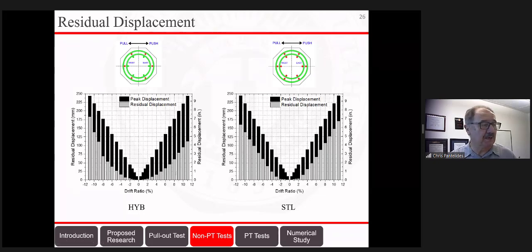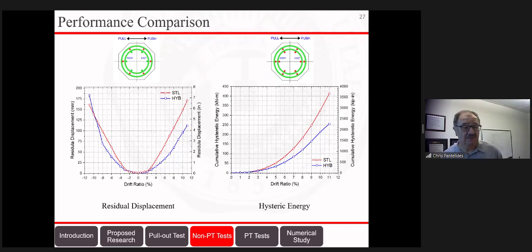So the other part here I want to talk about is this first graph on the left, which explains the difference between the steel, which is the red line, and the hybrid, which is the blue line, regarding their performance. So if I draw a line roughly, let's say at 25 millimeters, a horizontal line, you can see that the steel will exceed that at about 3%, whereas the hybrid can go up to 5% drift and still be okay. And then this graph on the right shows a comparison of the hysteretic energy. Hysteretic energy is the ability of the column to absorb the earthquake input energy, and we determine this by calculating the area of the hysteresis loop.